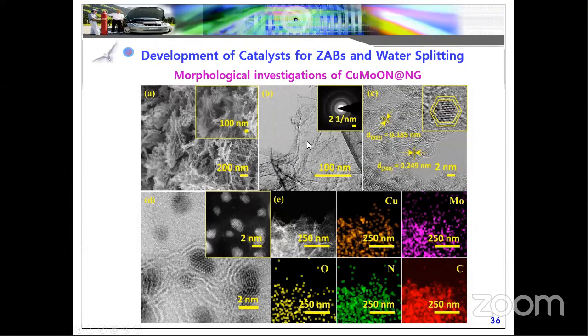And what is the role of nitrogen? Nitrogen should increase the conductivity compared to normal graphene, and the electron transport kinetics will be high compared to normal graphene. That's why we are using nitrogen-doped graphene. In these catalysts, you can see the particles are almost 2.5 to 3 nanometers, and the particles are encapsulated by small nitrogen-doped carbon shells.